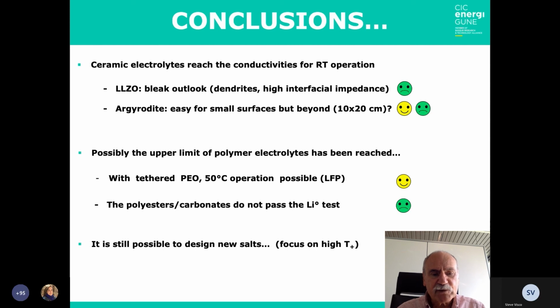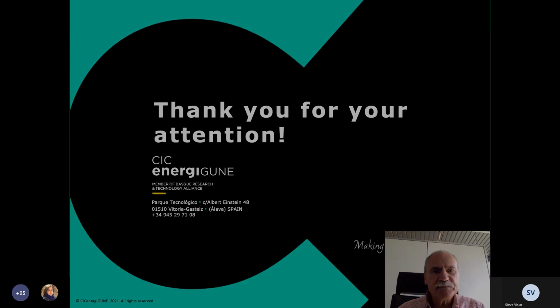It is still possible to design new salts, and we are focused on high T+, T+ equal 1 for the grafted nanoceramic, T+ equal 0.4 for the hydrogen bonded anions. And with one of the hydrogen bonded anions, we have shown that the SEI building properties are extraordinary. At this point, I want to thank you for your attention.